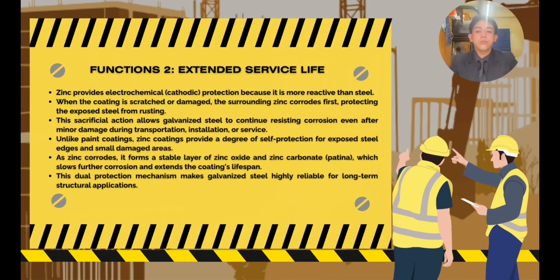The second function is extending the service life, as zinc provides electrochemical cathodic protection, as it is more reactive than steel. When the coating is scratched or damaged, the surrounding zinc corrodes first, protecting the exposed steel from rusting. This action allows galvanized steel to continue resisting corrosion even after minor damage during transportation, installation, or service. Unlike paint coatings, it provides a degree of protection for exposed steel edges and small damaged areas, where it forms a stable layer of zinc oxide and zinc carbonate, which slows further corrosion and extends the coating lifespan, which makes the galvanized steel highly reliable for long-term structural application.